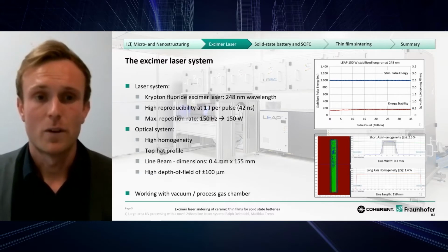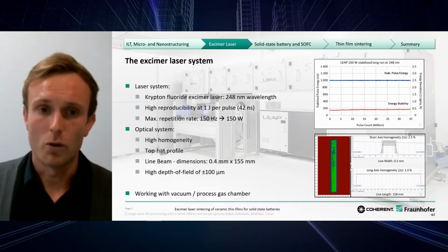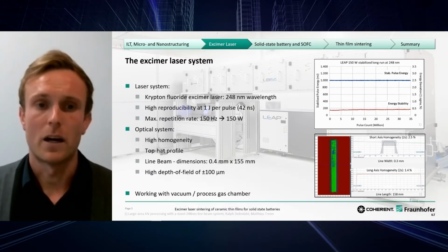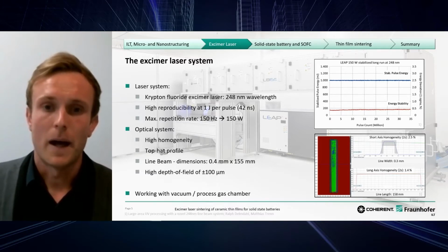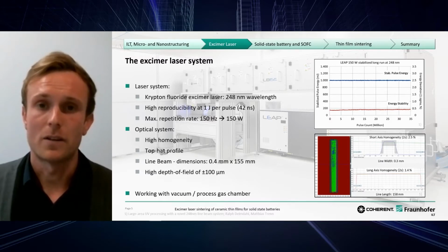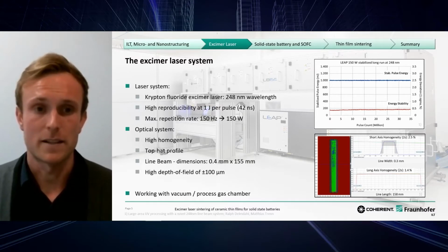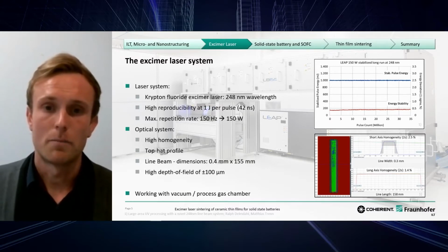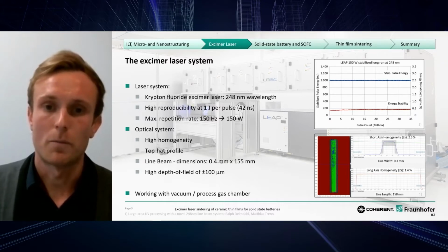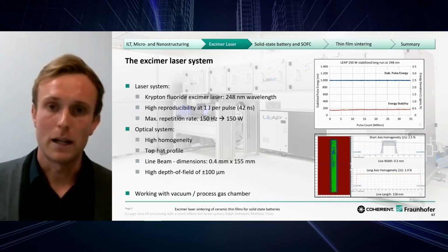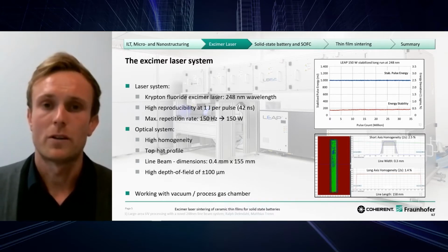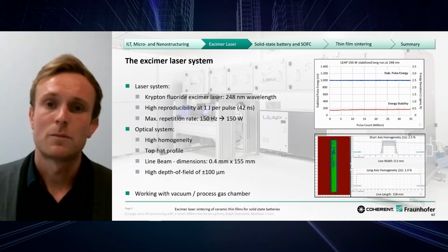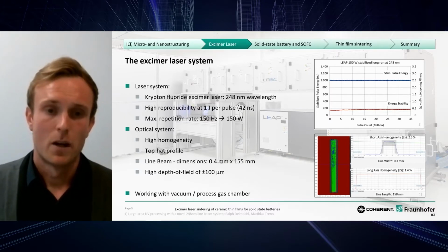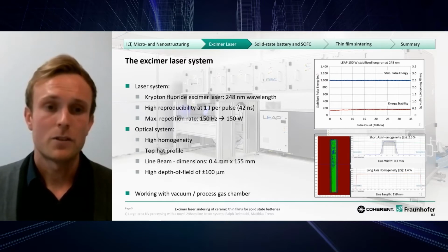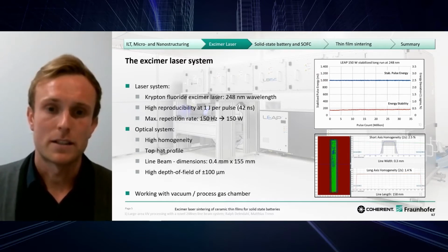The laser operates with a gas mixture of krypton and fluoride, resulting in a wavelength of 248 nanometers. That's very short, and due to that we also have very short optical and thermal penetration depths, which is very good for material processing. And due to its high pulse energy, shown in the top right, of 1 joule per pulse, and its maximum repetition rate of 150 Hertz, we can obtain a maximum output power of 150 watts, which is pretty large.